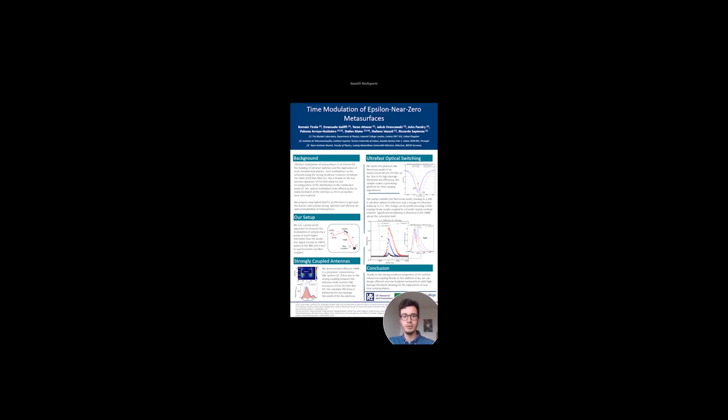Now, the main limitation in absolute efficiency of this system was the low damage threshold of the gold nanoantennas. So what we tried to do instead is to deposit an unstructured layer of gold on top of the ITO and start shining from the substrate. So we are now accessing the Berreman mode of the ITO, which also shows very strong field enhancement, but we are not burning the gold anymore, and we can explore high saturation physics.